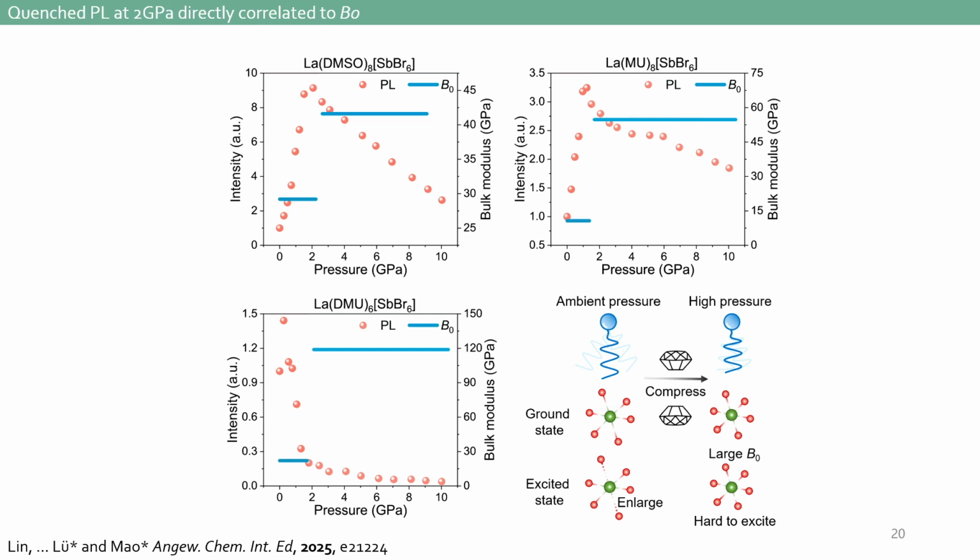especially they have shown a much similar trend, but also slightly different, because you can see how the intensity of the emission has peaked at around 2 gigapascals, and then it just starts to decline. So the first two compounds don't show a dramatic decrease, but for the last one, it shows a much more instant quenching.